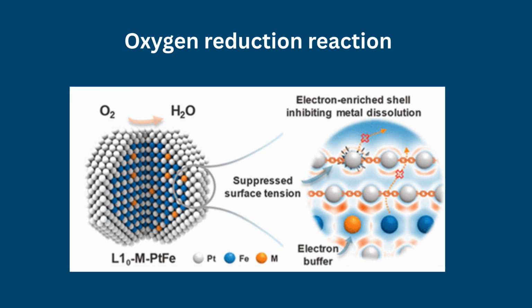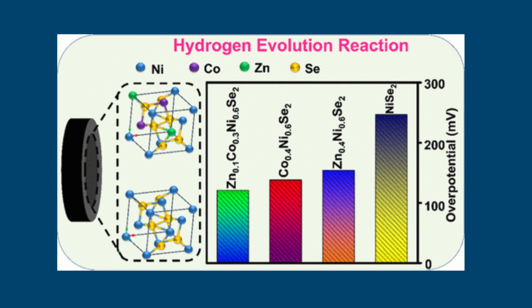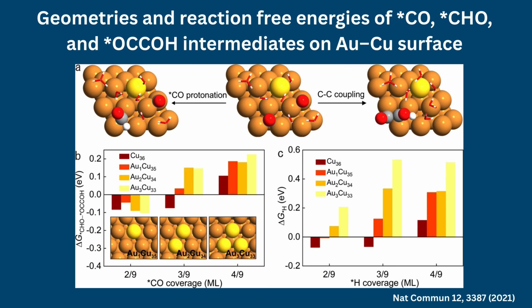MMNPs are also extensively investigated for electrocatalytic reactions, including oxygen reduction, oxygen evolution, hydrogen evolution, carbon dioxide reduction, and methanol oxidation. Pt-based HEA-MMNPs containing Fe, Co, Ni, Cu, and Zn have demonstrated enhanced oxygen reduction activity and durability relative to commercial Pt catalysts because of optimized adsorption energies and improved resistance to catalyst poisoning.